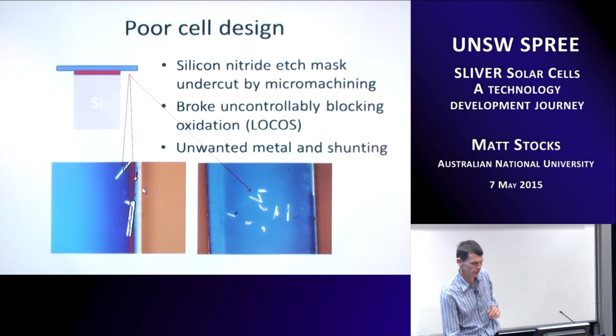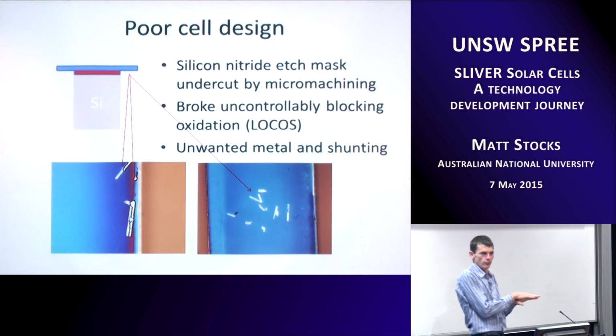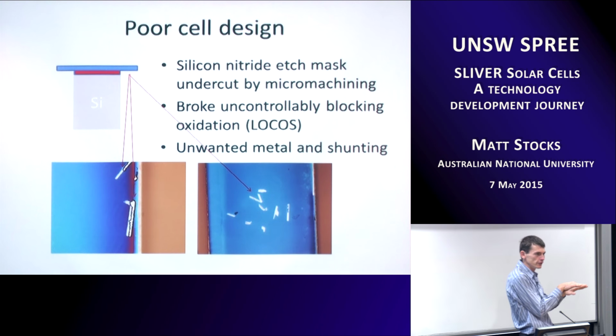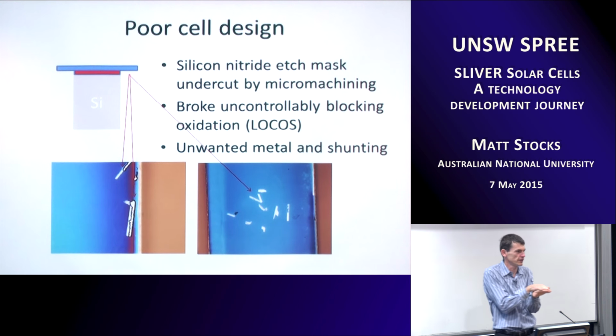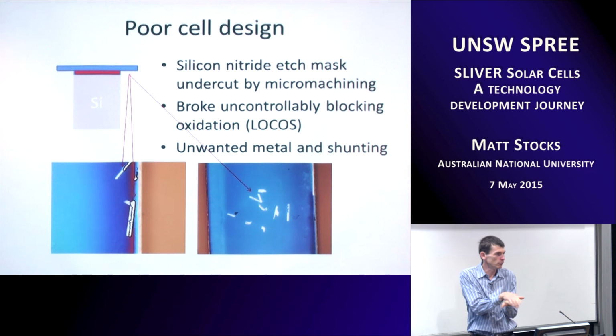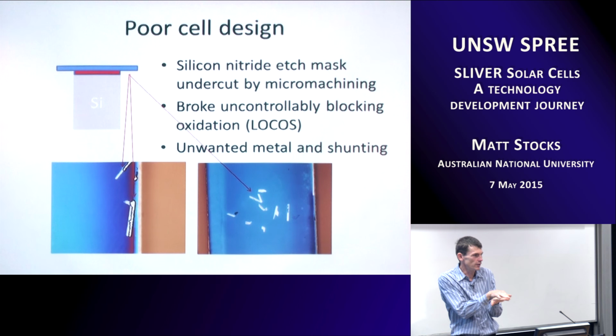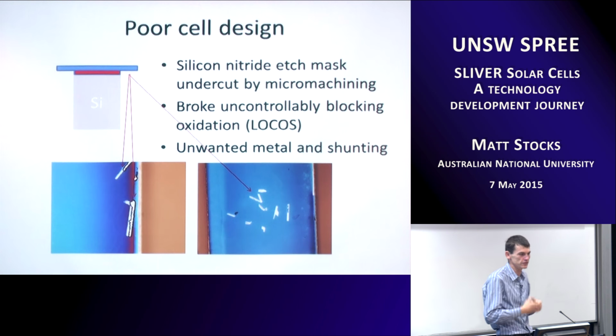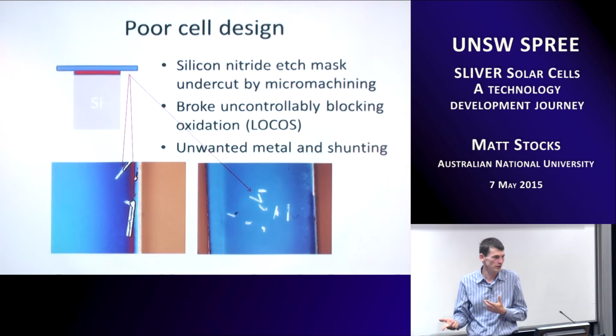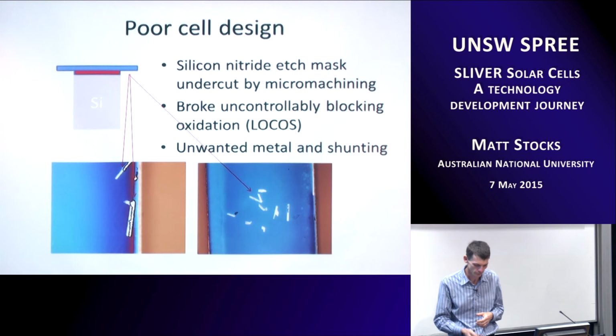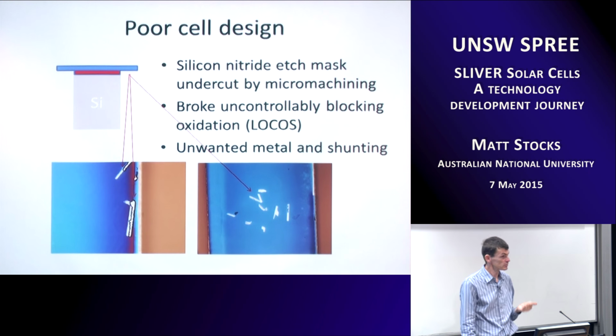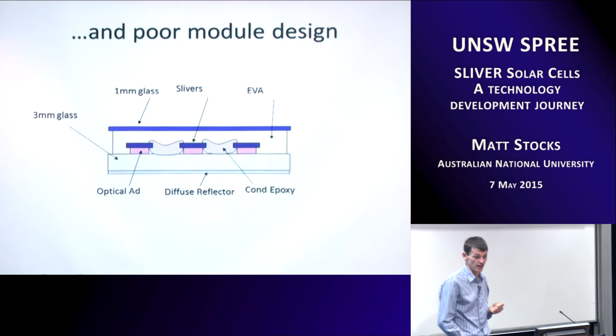So this is a good example of it here on the left. We had this nitride flap sitting on the surface. We tried to do an oxidation to passivate the surface. The nitride blocks that oxidation. During some of the other processing, the nitride flap lifts off a little bit. There's no longer anything on the surface to passivate and protect the surface, and we get unwanted plating in those locations, which some of the time then also leads to shunting. So we started off with that sort of a problem.